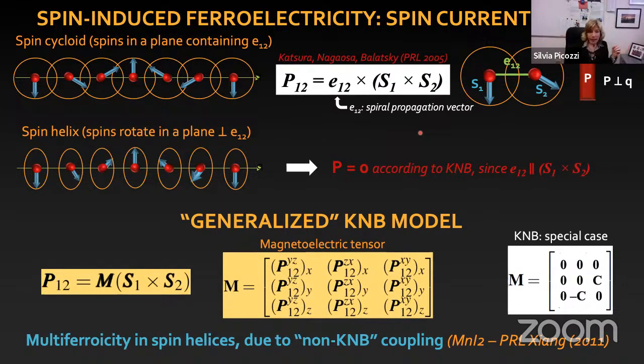But we thought we could extend it, and this was actually done not by us, but far back in 2011 by Xiang. So what he and co-authors wrote was that you can still think that you have a contribution to polarization by the cross product of two spins times not just the propagation vector, but times a matrix, which you can call a magnetoelectric tensor. So of course, this KNB simple model is a reduction. This is a more general framework. And if you have your KNB model valid, then your tensor has a specific form with just one independent parameter. And so with DFT, we estimated this.